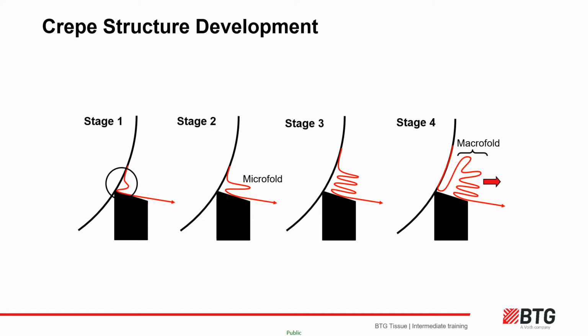Optimum creping is then a succession of microfolds formed after the initial fold is forced out of the coating pocket by the creping blade, i.e. stage 1 and 2. Microfolds build up on top of the creping blade until they naturally grow too large and exit the blade as a macrofold at stage 4. Crepe ratio, that is the difference between the Yankee and reel speeds, allows this process to develop naturally.